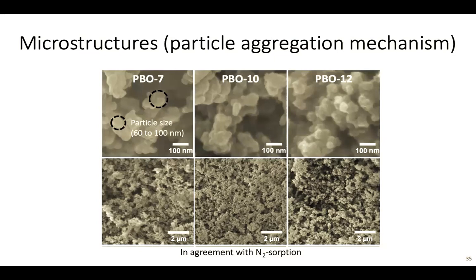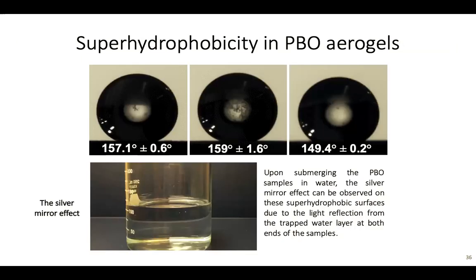The SEM remarkably is also consistent with N2 sorption. The particles are aggregated on each other. It's packed. That's why this aerogel is literally stiff, but it's brittle.